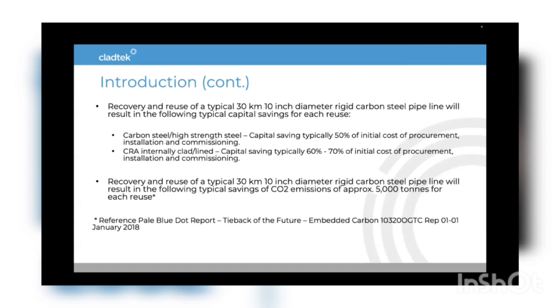If we compare, what does reuse mean in terms of cost reductions compared to the existing solutions? When we compare it for risers, the installed cost is typically around 50% of the current methodology, and that is not considering the possibility of reusing the pipe. If you do reuse the pipe, looking at a 30-kilometre, 10-inch tieback, the CO2 savings is around 5,000 tonnes per pipeline, so quite significant.